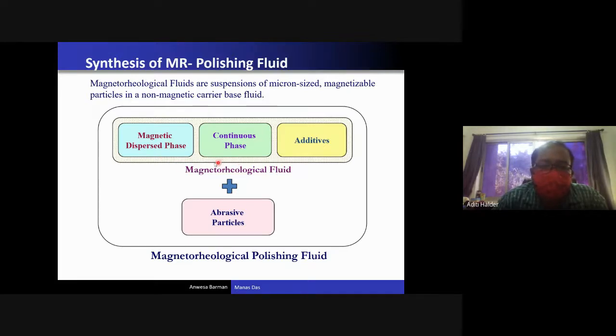To reduce the sedimentation problem, we have to use a thickening agent. As a thickening agent you can use lithium grease or any other thing. If you mix this grease with the base media, the base media will become a little bit thicker, and these magnetic particles will get less chance to deposit at the bottom. So that is how you can reduce that kind of problem.